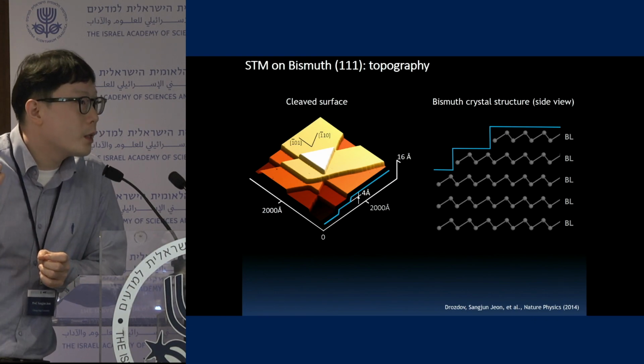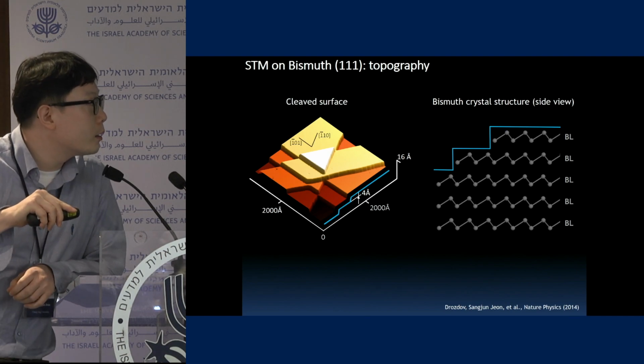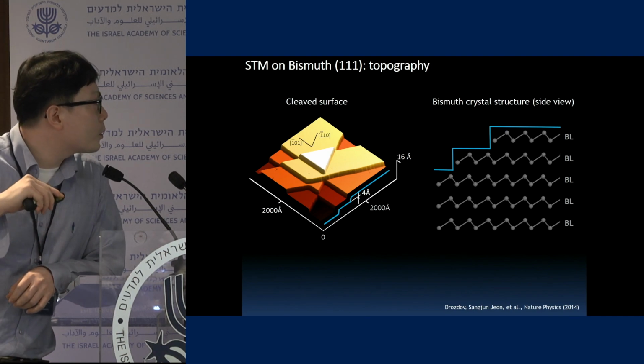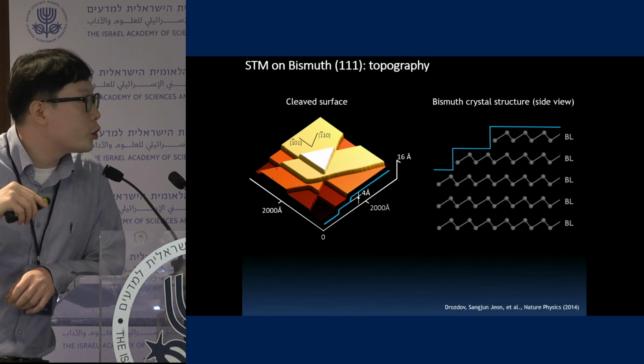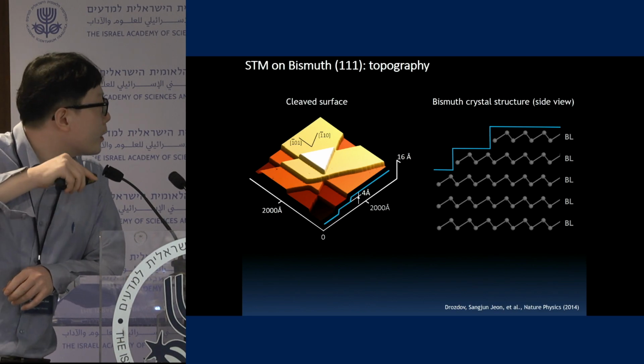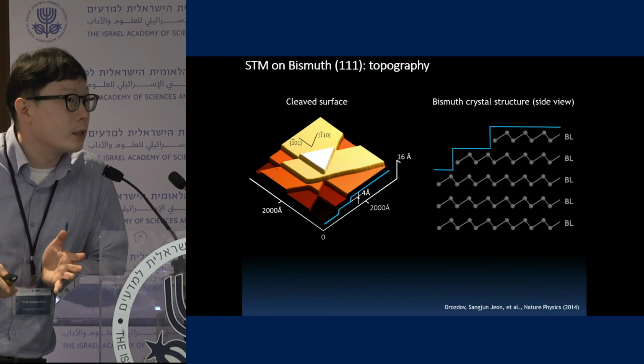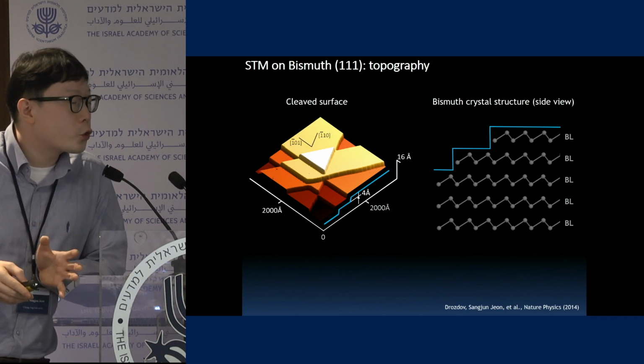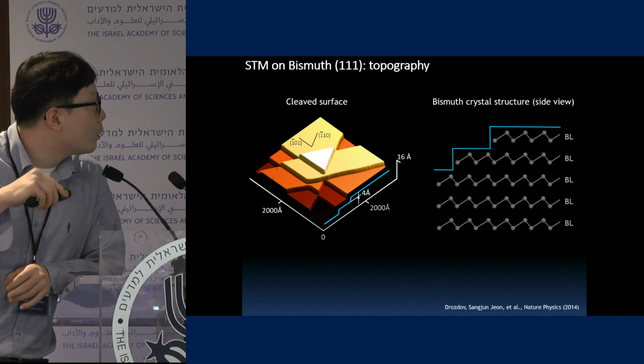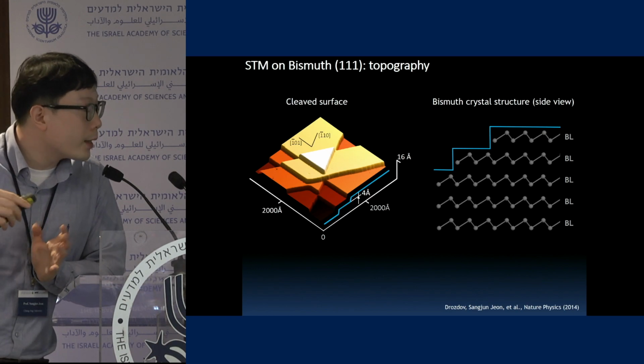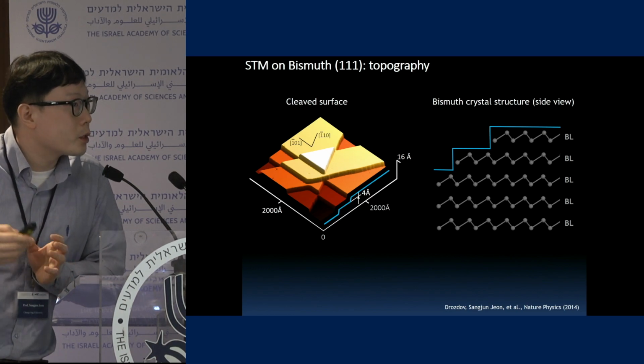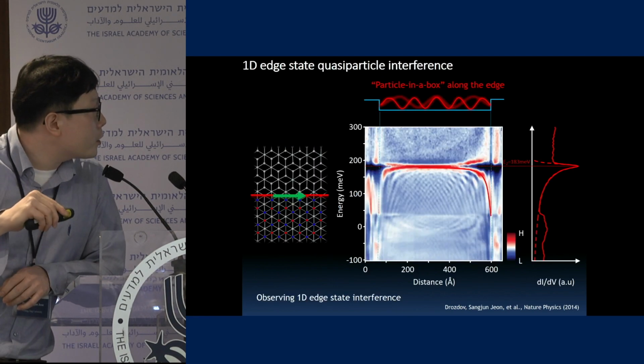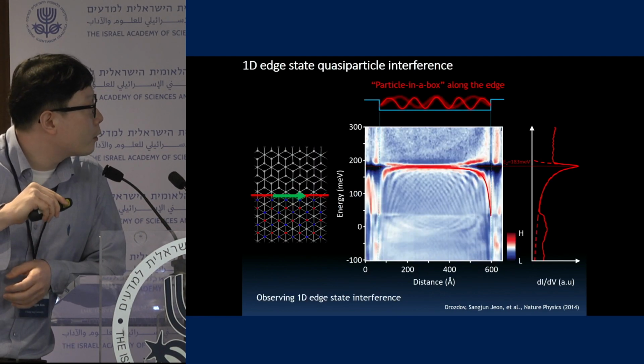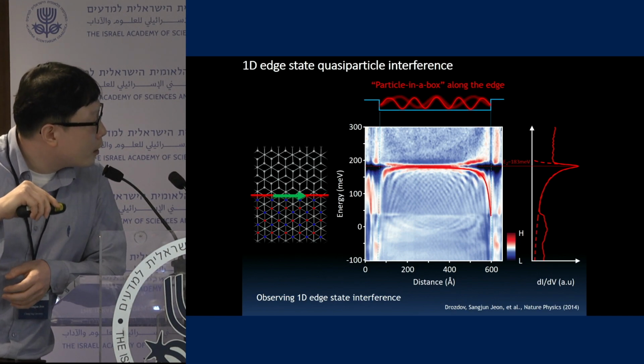that behaves as a quantum spin Hall system when it is in a single bilayer system. But we cleave the bulk bilayer system and measure the surface states and edge states. For example, here, these are all edges of the bismuth, and we also measure the surface states here. And then we found very strange electron states of all surface states and edge states. Mainly they are coming from the strong spin-orbit coupling. And especially if you measure the interference pattern along the edge of the bismuth, we found that there is a very nice interference pattern.